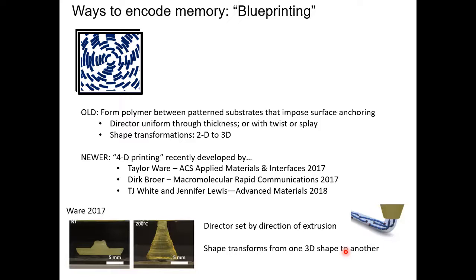And these materials can also undergo shape transformations. When we blueprint thin films between two pieces of glass, we make a very thin piece of polymer that can go from a two-dimensional flat object to a three-dimensional object. It can curl, it can twist, it can bow, it can bend, it can do all kinds of things, 2D to 3D. But once we're doing this printing jazz, we can print a three-dimensional object that transforms into another three-dimensional object. And what's really interesting is it can undergo instabilities where it basically hops and pops, just like those little toys where you deform them, put them on the table, wait a minute, and they undeform themselves and pop off the table. These things can pop as well. They can have very rapid shape transitions.